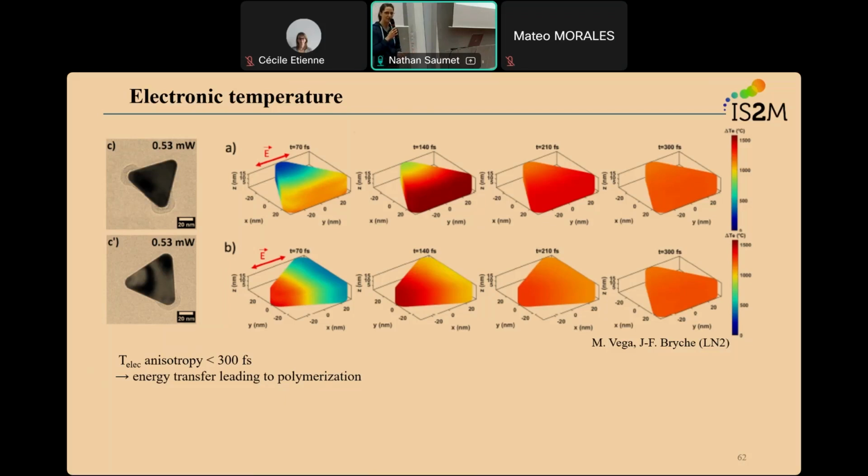It's a dielectric media, so it's really hard to imagine an electron ejected from the particle behaving in the monomer and trying to find the thermal initiator and break it. I don't think that occurs. So it's more a phonon-phonon interaction, which will make the molecule vibrate and somehow create heat.